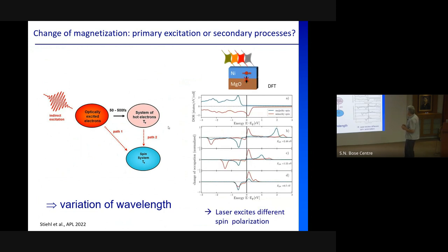For example, this is the density of states of the majority electrons, blue, and red minority electrons. That's a DFT calculation done in the Schneider group at Kaiserslautern. When you take different wavelengths of lasers, 0.7 electron volt, the infrared laser, you mainly excite minority electrons. When you use 2.5 electron volt, it's mainly majority electrons that you excite. So if the optically excited electron does the job,